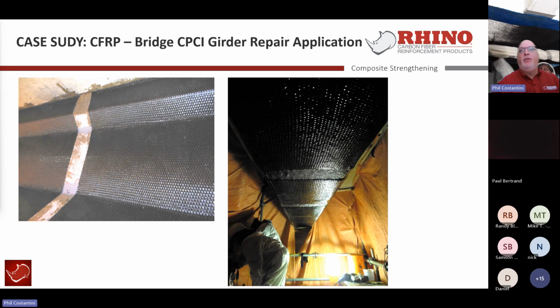Yeah, and here's how we sustain that. See this containment area? We didn't want exterior elements to affect our moisture content. We wanted to maintain a certain temperature variance throughout. Most importantly, while we were doing that, to get it to the point where we can apply the carbon fiber and not wait 28 days to go back and reestablish lane closures and all that. And so we kept this internal environment exactly the same for 24 hours for 10 days.